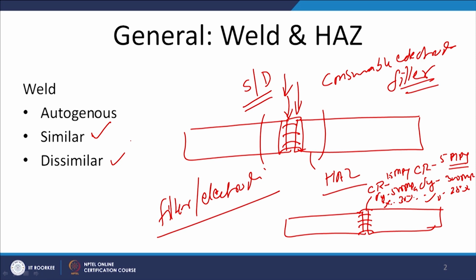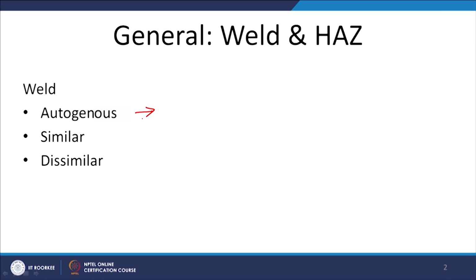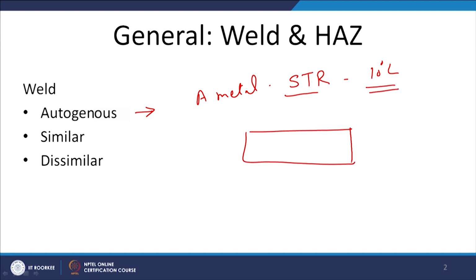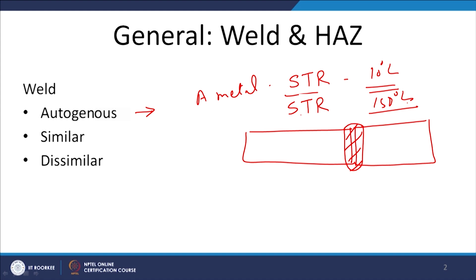There are some issues with the autogeneous welding process as far as weldability is concerned. Like a metal which has a solidification temperature range of just 10 degrees, the issues related with the weld metal are very limited, especially with regard to solidification cracking. But when the solidification temperature range becomes very wide, like say 150 degrees centigrade, then even autogeneous welding does not help to eliminate it. Even simple fusion welding, where just the faying surfaces are brought to the molten state and subsequently solidified, sometimes leads to solidification cracks at the center of the weld.